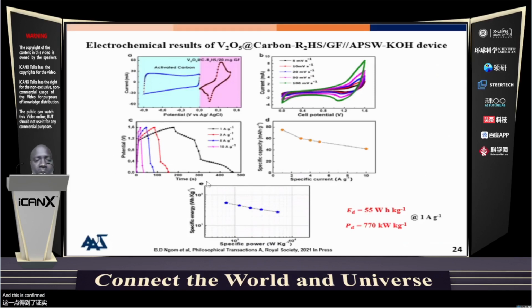And this is confirmed by the potential discharge behavior, as the nonlinearity of the discharge is confirming the supercapacitor's behavior of the material. And all this turned into an energy density of 55 watt-hour per kilogram, as we moved from 33.5 to 55. So you could see how the graphene that we incorporate into the matter has enhanced the energy density of the electrode, even if we have a power density of 770 kilowatt per kilogram.